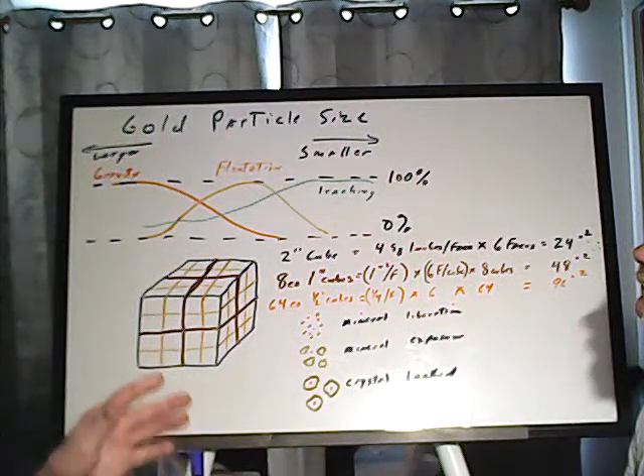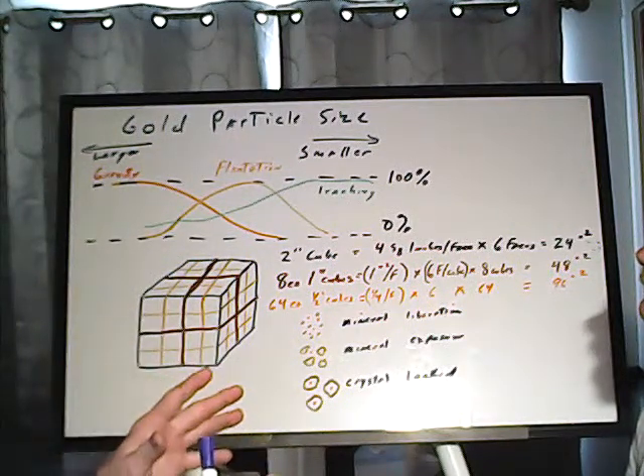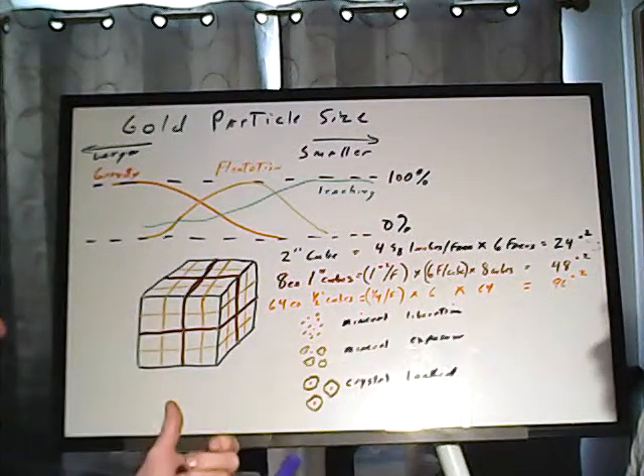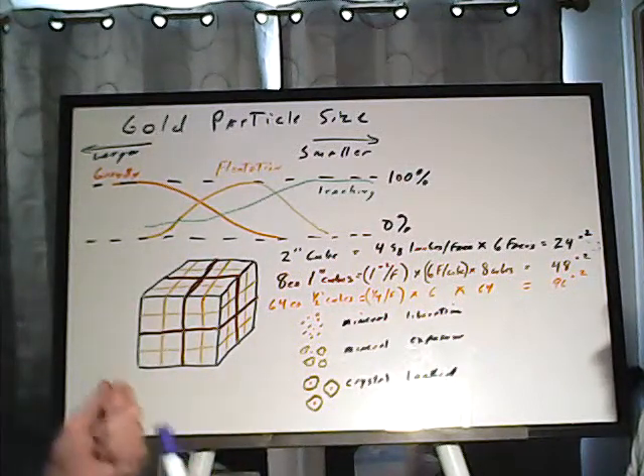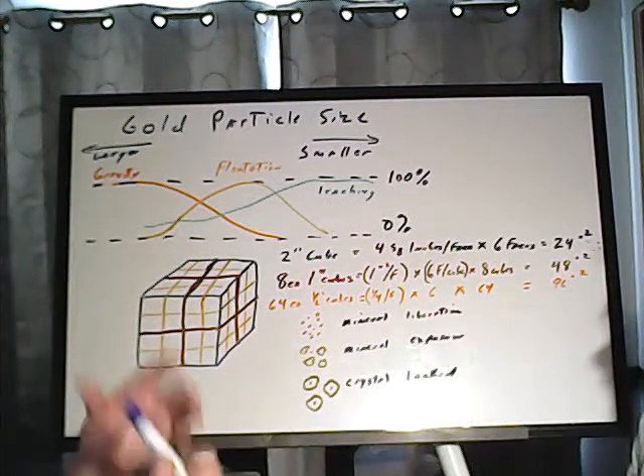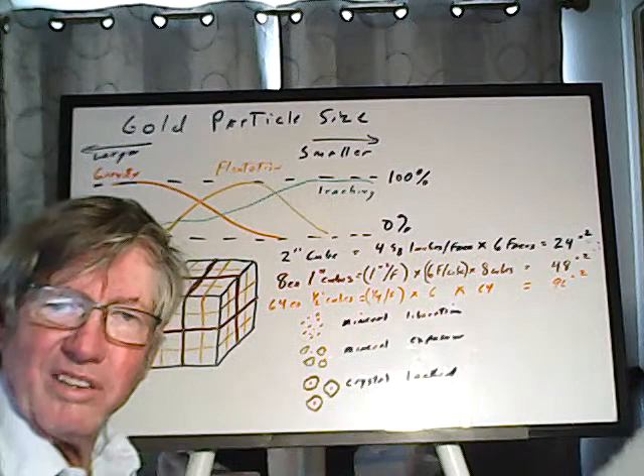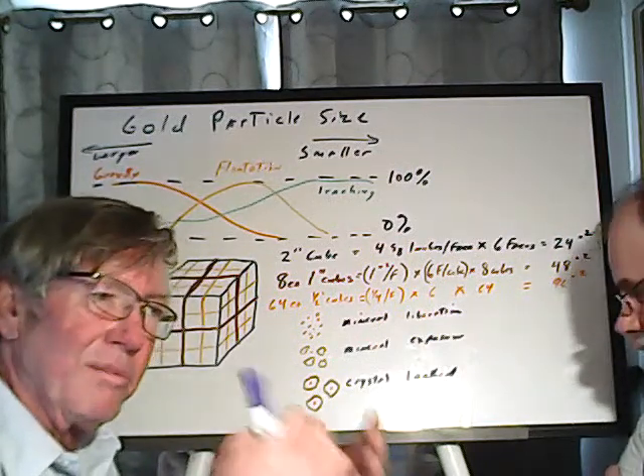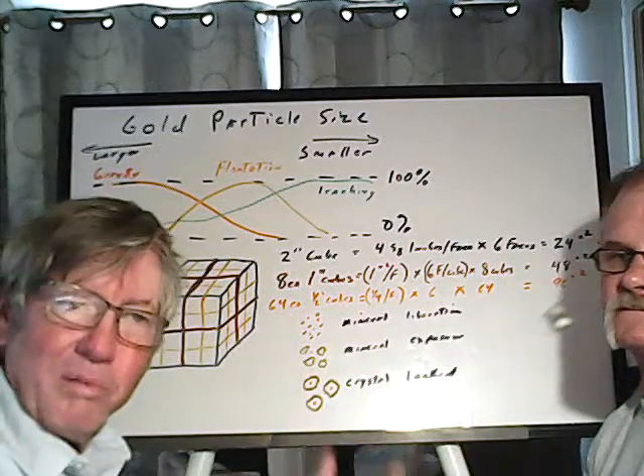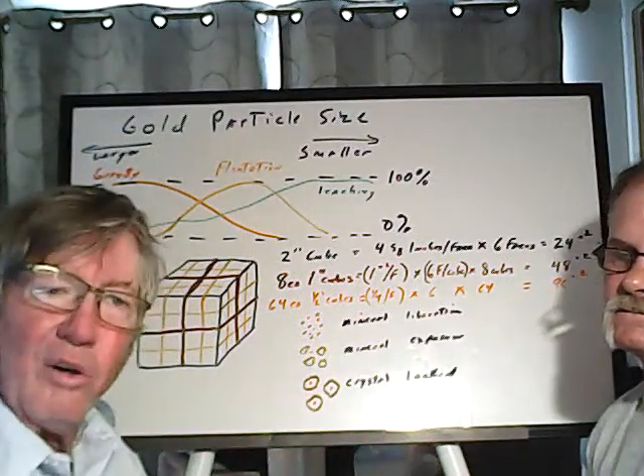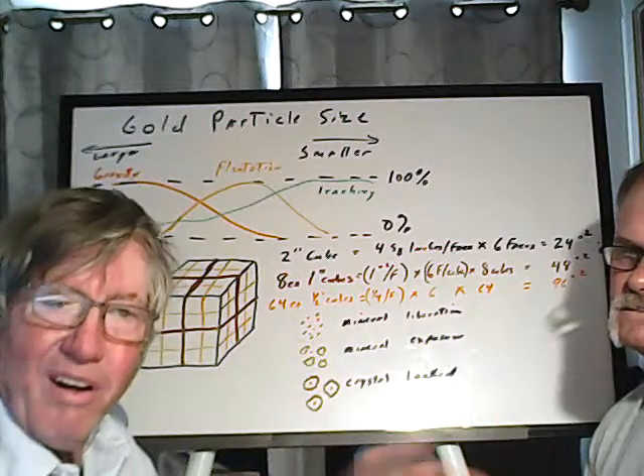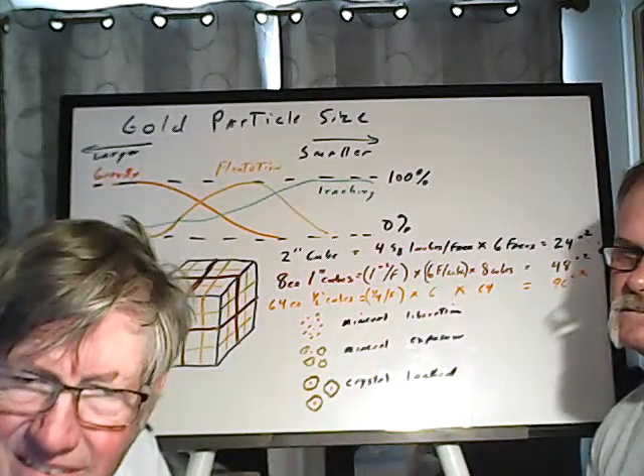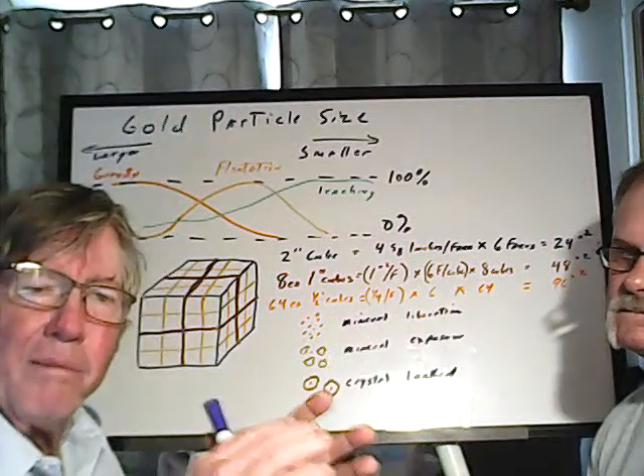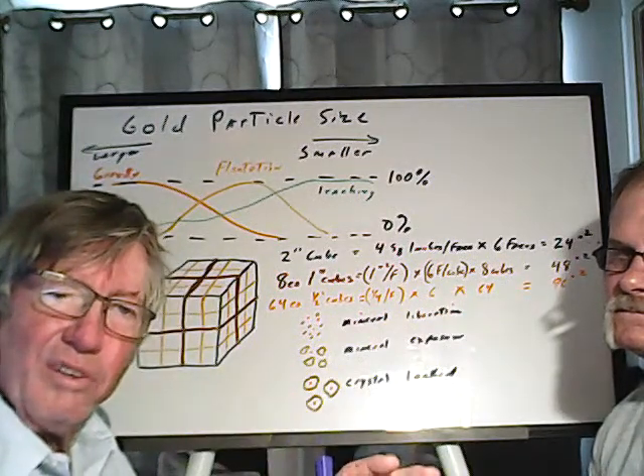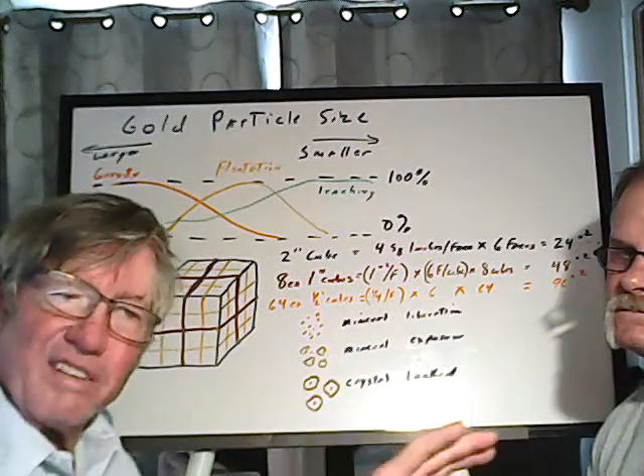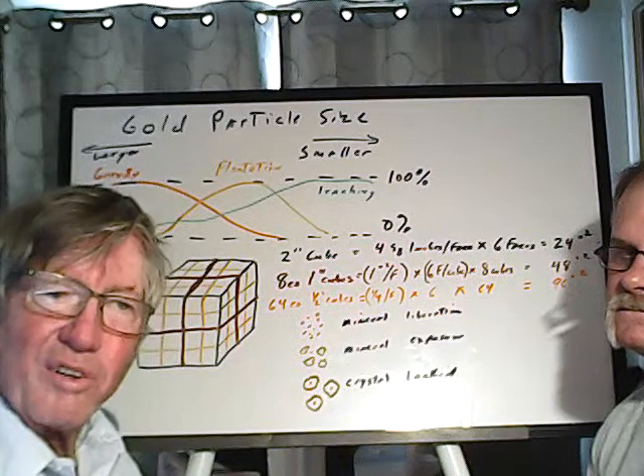And with coarser gold like that, and it's already broken free, in almost every case, the most economic way to get it is what they call a gravity separation. This is where you use the difference in density to make the gold go someplace, well, the rock goes someplace else. A sluice, a jig, a gold pan, a riffle table, all those are gravity techniques. They rely upon the difference in density of the gold to make it do something different than the rest of the rock, which is less dense. That's called a gravity separation.